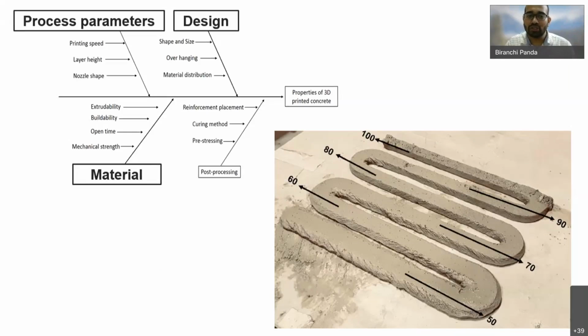So what we do is stop the machine and take a break before printing more layers, because by that time the material yield stress will have improved, so the addition of more layers is not going to disturb the structure. So this is all about how you deal with material. But in other 3D printing, we also deal with process parameter design. Similarly, in concrete printing also, the process parameter design is important.